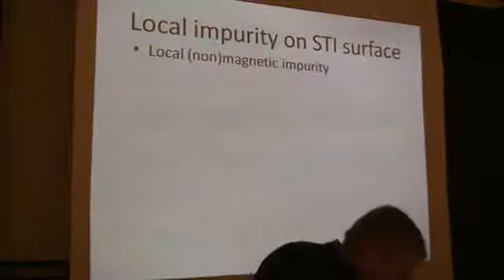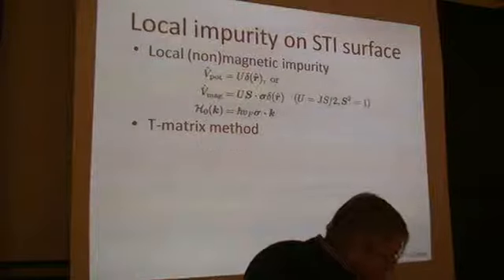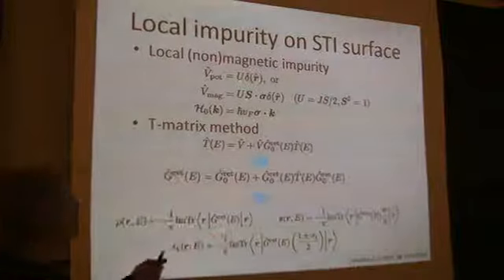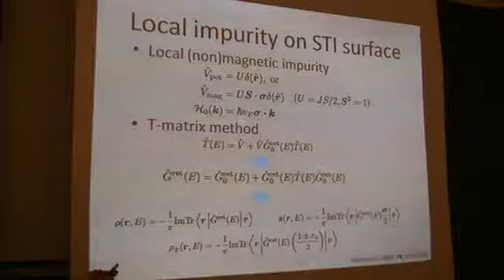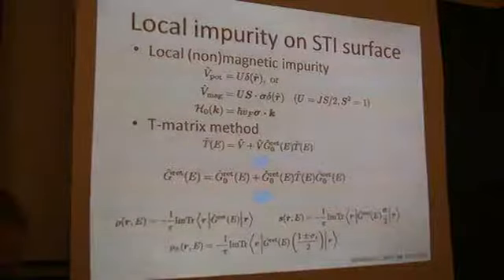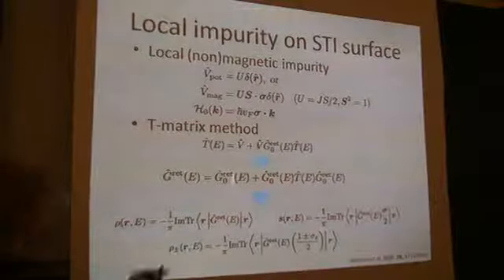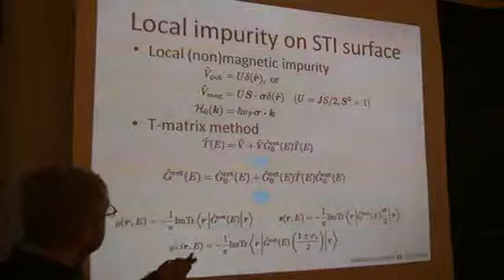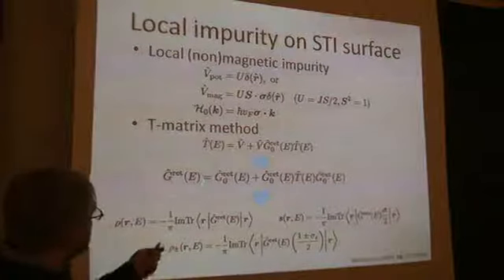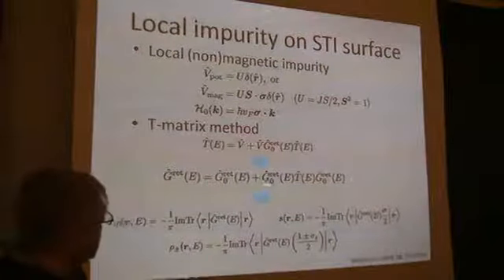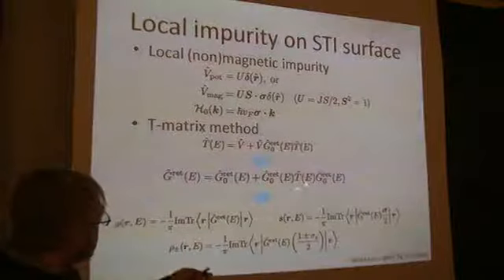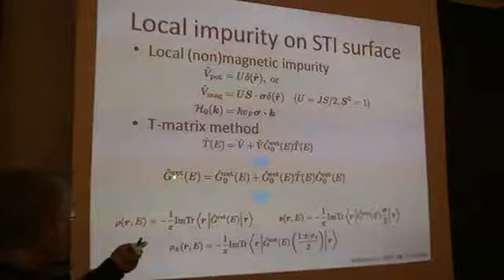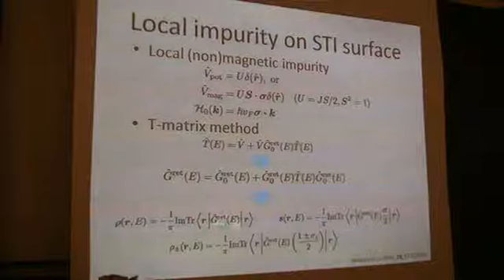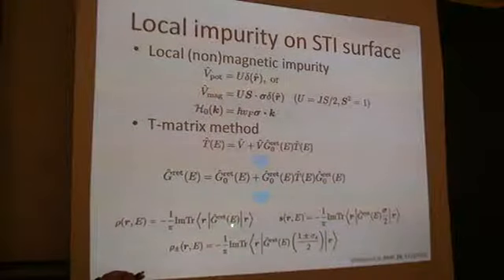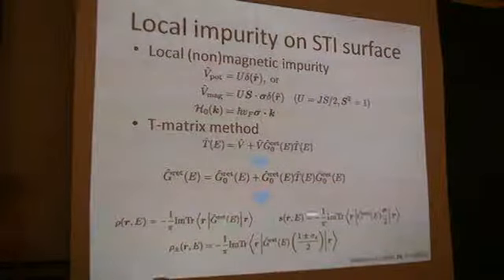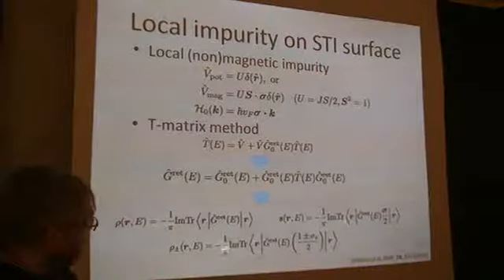So just to repeat the machinery, we will put in the local impurity, which will be magnetic or non-magnetic. I will use this Dirac Hamiltonian, assuming that I have some protection if I have a gapped bulk. And then I will proceed with calculating the T matrix for multiple scattering and then plugging it back into the full Green's function. So this piece here measures the modifications of the local density of states. And from this Green's function, I can take the imaginary part on the particular site and measure what the total density of states looks like as a function of energy. Or I can look at the spin projected density of states, spin up and spin down.